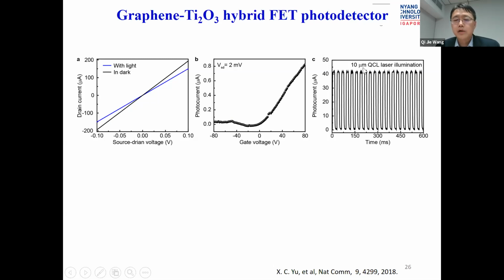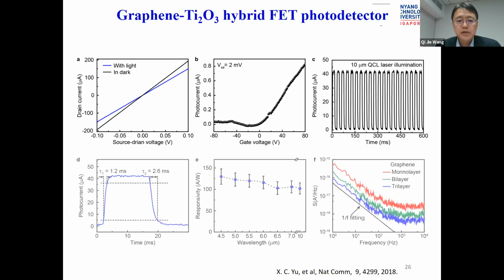Okay, so here the figure on the top right shows the photoresponse of such photodetector with a 10 micron laser illumination. Okay, it has relatively good photoresponse speed at around 1 millisecond, and a very high responsivity beyond 100 amperes per watt across a wide range of wavelength region.